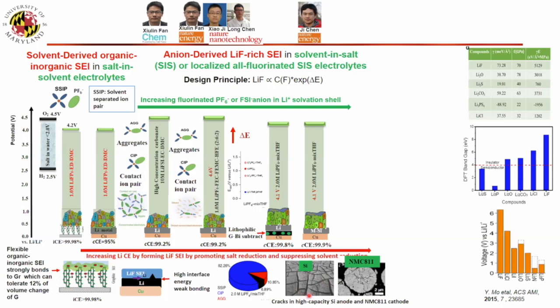For silicon, we know that micro-size silicon cracks. With a traditional SEI, if the silicon cracks, the SEI also cracks, electrolyte penetrates, and then they form SEI that separates the cracked silicon. If we have lithium fluoride and the bonding is so weak, even if the silicon cracks inside, the SEI can protect it, electrolytes cannot penetrate, and the pieces can still contact each other. So it's still working.